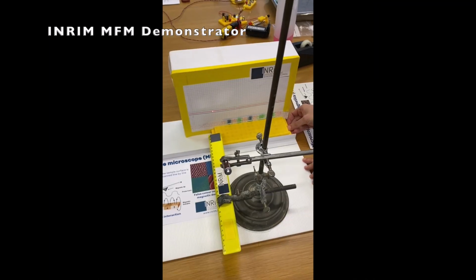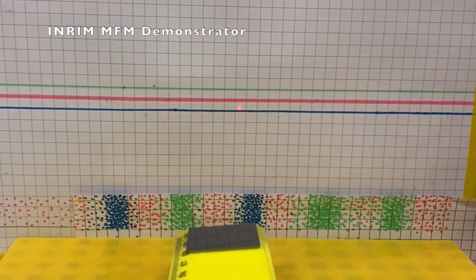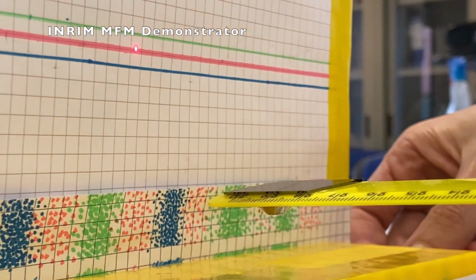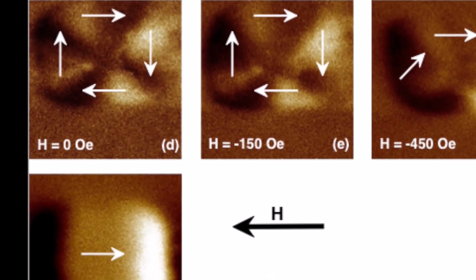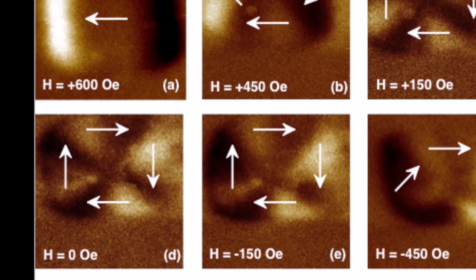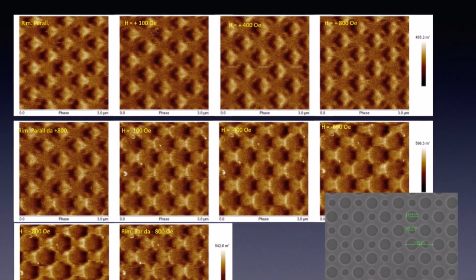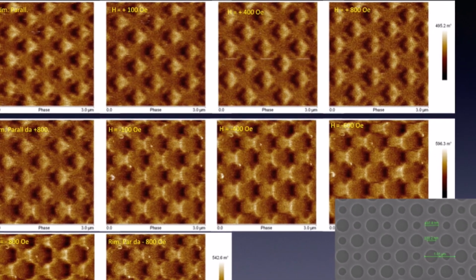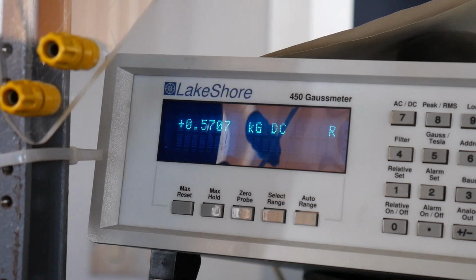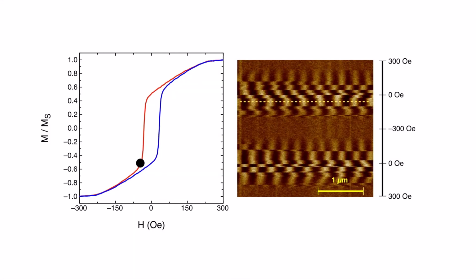The magnetic field gradients generated by the magnetization at the surface of the sample affect the dynamics of the magnetically coated tip and cantilever, allowing the reconstruction of the domain pattern. If you take care that your microscope has no magnetic components, you can then apply a magnetic field and induce a variation in the magnetic configuration of the sample. You can even synchronize the magnetic field to the scanning of the tip on the sample surface. In this way, you collect a single image that represents the whole evolution of the domain pattern of the sample as a function of the applied magnetic field along a given profile.